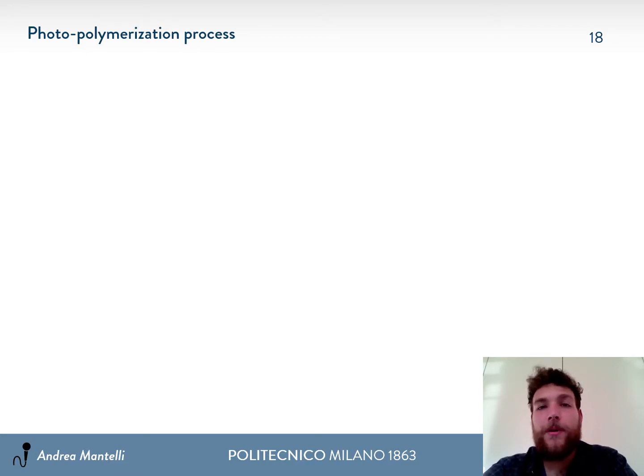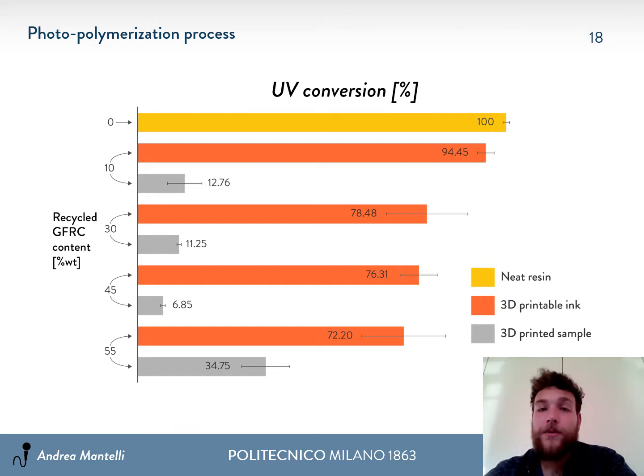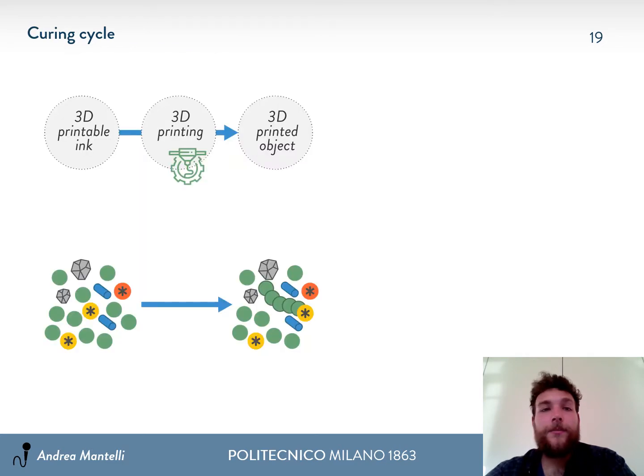Since we use a photoactive polymer, we tested the reactivity, and as you can see, with increasing content of recyclate, the UV conversion decreases for the 3D printable inks, and so part of the monomer is not reacted. Moreover, after 3D printing, the material is still photoactive, and this is due to the low residence time under the UV light during the process. From this test, we are able to define an optimal curing cycle, and going from the 3D printable inks to the 3D printed object, we have a material that is partially polymerized, and in this way the shape retention is assured.